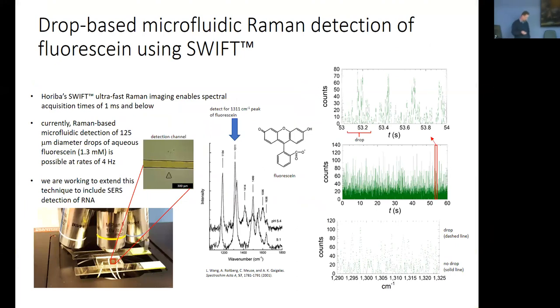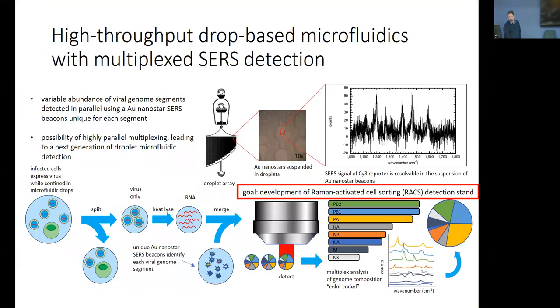Now, fluorescent markers are not always the most sensitive. They're not always the easiest to use. And Raman signals can be more specific. So they are working on basically developing a Raman-activated cell sorting. There is evidence that in surface-enhanced Raman, you can very sensitively detect some of these compounds that they want to detect. But they are really working on trying to do this in microfluidic devices. So what they are hoping to do is to use beacons, in this case, gold nanoparticles that can enhance the Raman signal, and have those linked to certain pieces of nucleic acids that link up with certain viral populations, so that they can ultimately detect and sort them in their microfluidic devices.